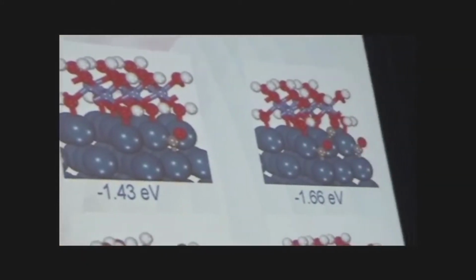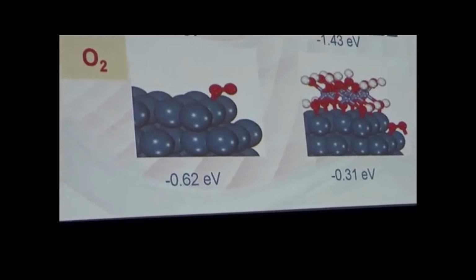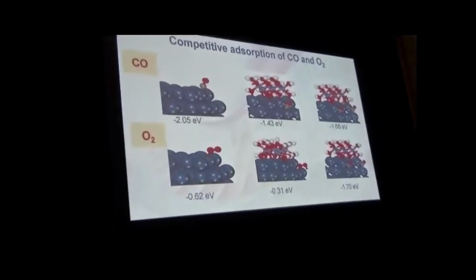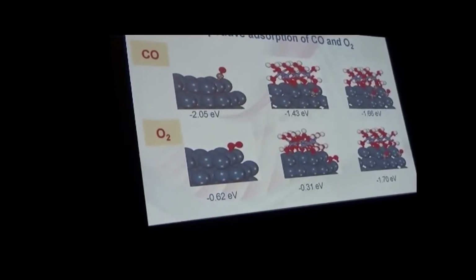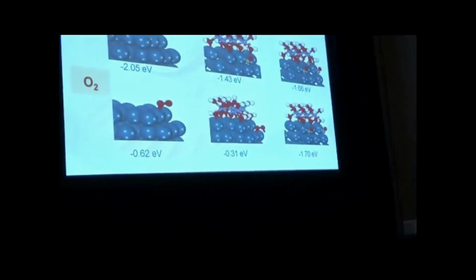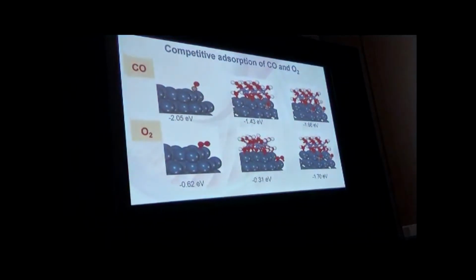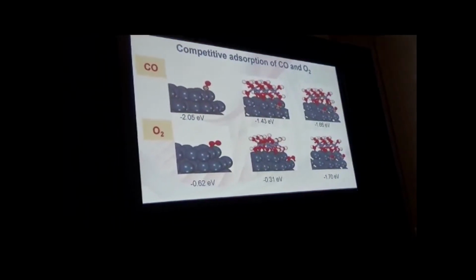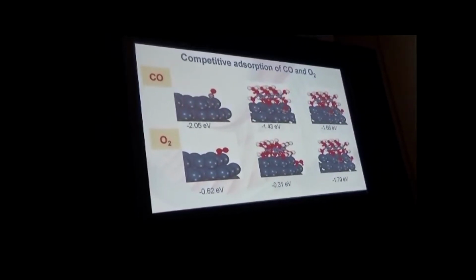For CO oxidation, one of the key parameters is the adsorption energy of CO and O2. For the clean surface, it is the Pt step site for the Pt nanoparticle. We can see that the adsorption energy of CO is much stronger than O2. So in this case, we cannot achieve low temperature CO oxidation. Even when we cover the platinum with iron oxide, the CO adsorption is still much stronger than O2. When we remove one hydrogen here, the O2 adsorption becomes much stronger. So O2 can be stabilized at the interface. So why is the interface very important? It can stabilize the O2 adsorption.